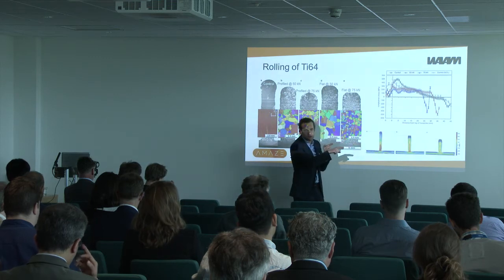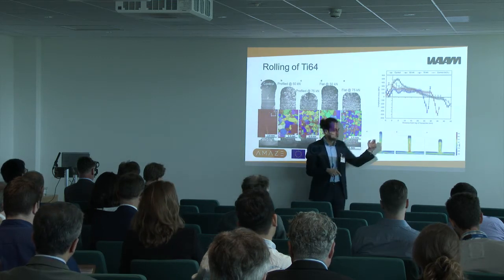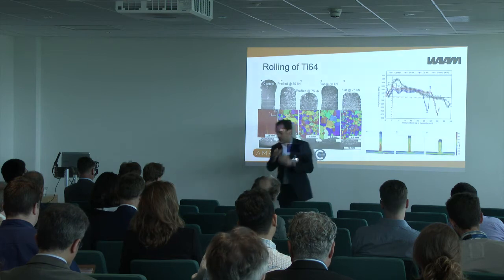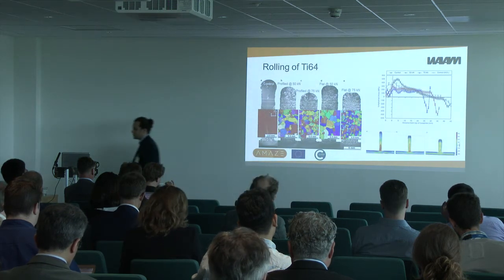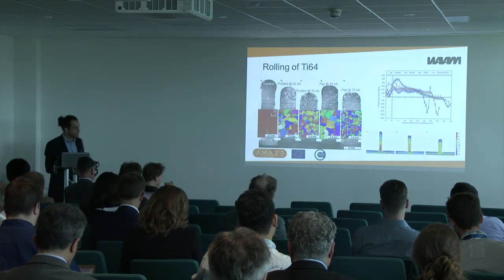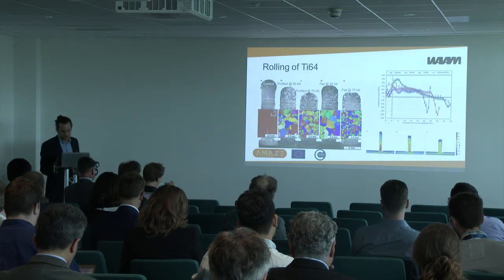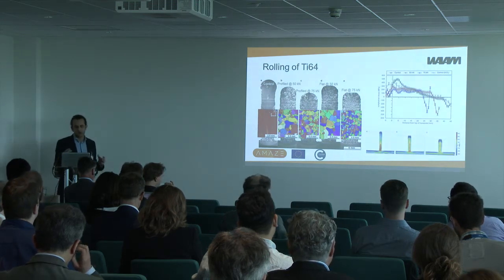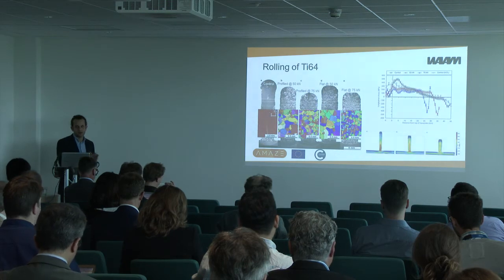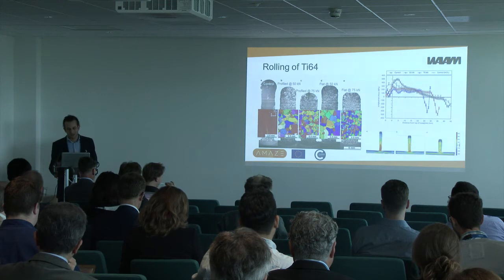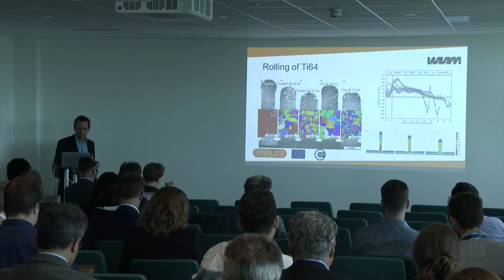But if you want to relieve the residual stress, the deformation has to happen in this direction, that of the longitudinal residual stress. So, yes, it's very good for mechanical properties improvement, but not as good for residual stress. Anyway, it doesn't matter because we know how to tackle this problem, as I said, either with the symmetrical building or with very good tooling with which the part is heat treated as a whole assembly.